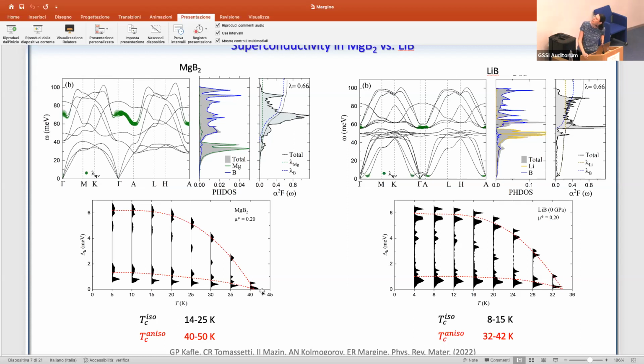Yes. Lambda indeed is very close. I should mention all these calculations have been done right now with the PseudoDojo stringent pseudopotentials from the Abinit library. When we compare, for instance, for MgB2 with older phonons done with other pseudopotentials, there are slight differences. I don't have the plot here, but we plotted against some experimental data, and this phonon dispersion for MgB2 is in much better agreement with experiment than previous calculations. But it's true that depending on what pseudopotential you use for MgB2, you may end up with values which can vary, like 0.7 I found in the literature with older pseudopotentials. So for the study that we've done here, for all systems we use the PseudoDojo pseudopotentials just to be consistent.